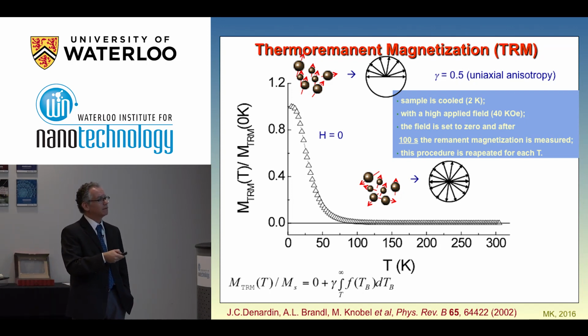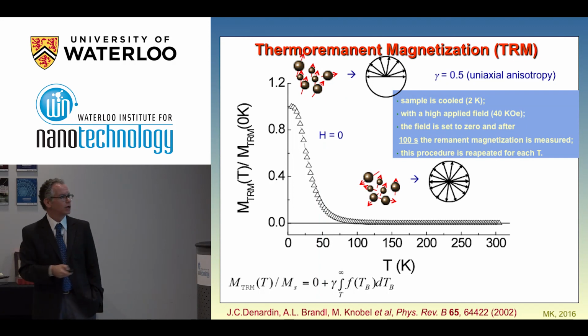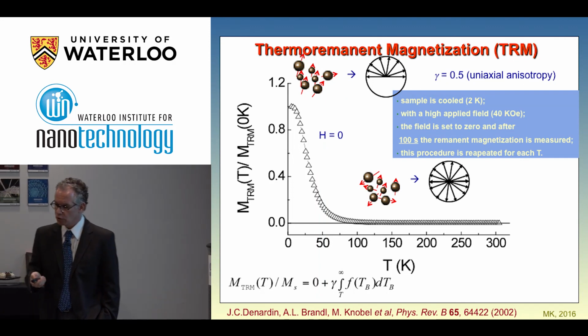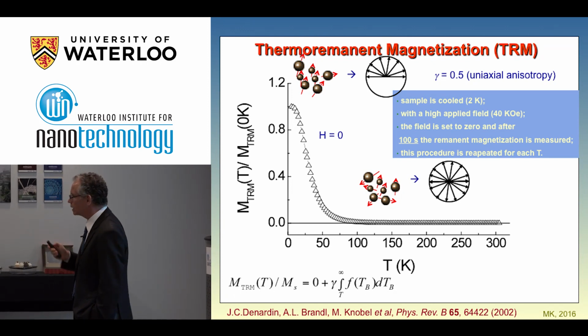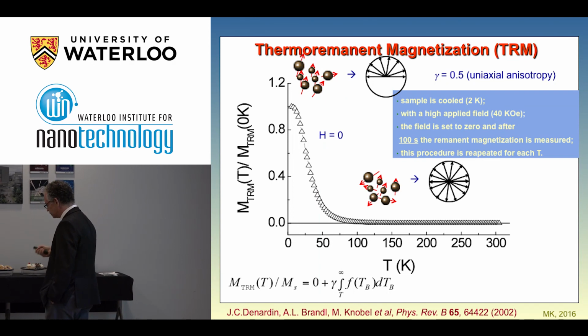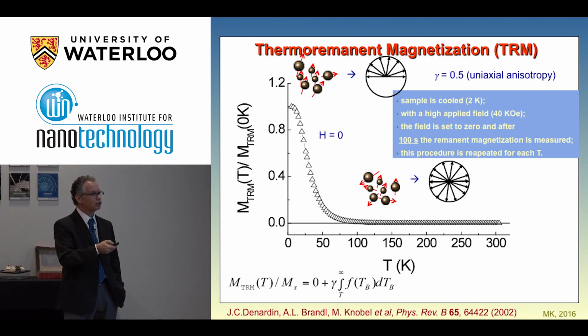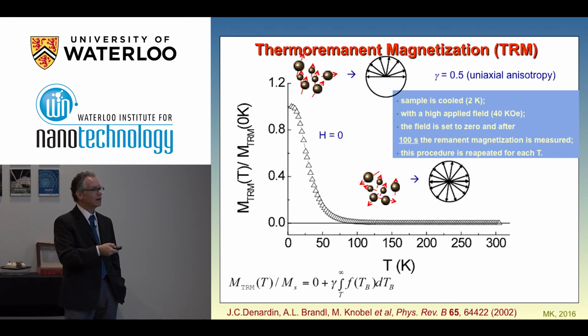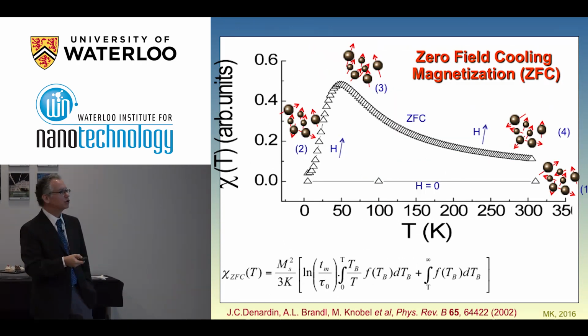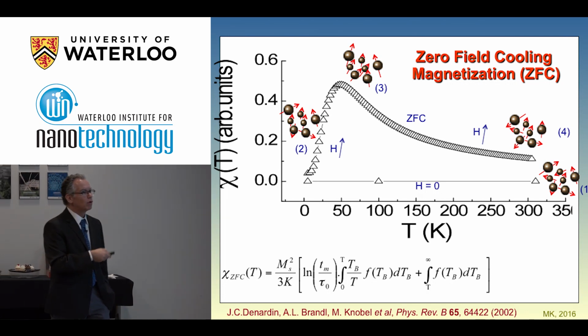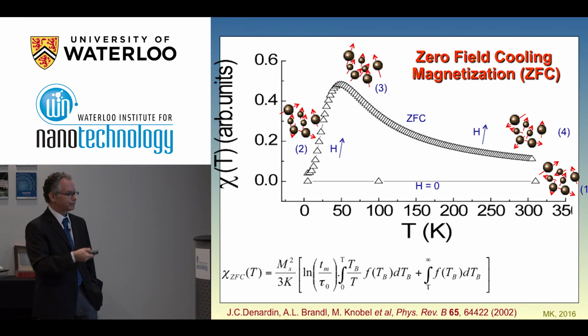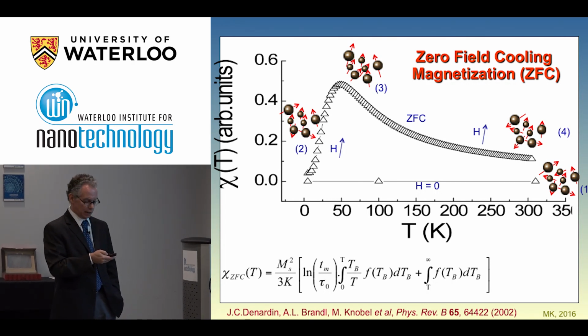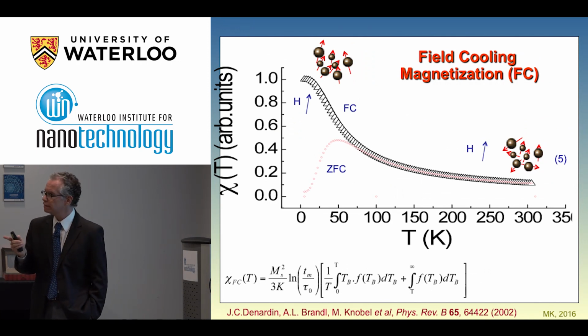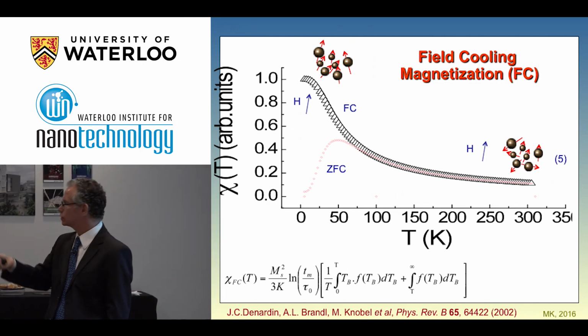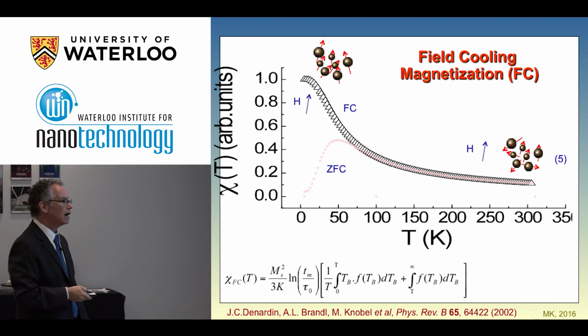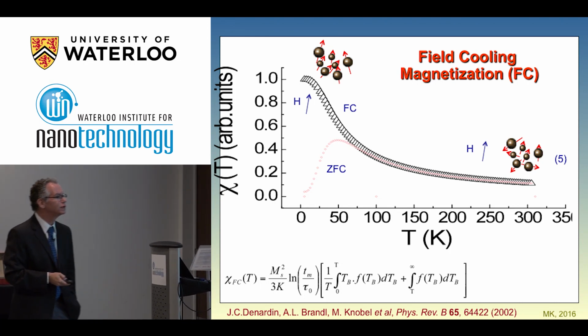And then, using this very simple approach, you can model very easily, really very easily, your experimental curves, your experimental data. So you have a distribution of particle sizes, and you can calculate the remanence and the temperature dependence of remanence, or you can calculate the susceptibility, and whatever you need for the system, you can very easily calculate. Of course, if you have the distribution of particle size and you have all the structural information available. So I won't go into the details of these things.